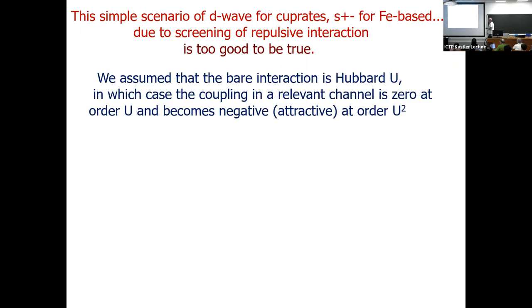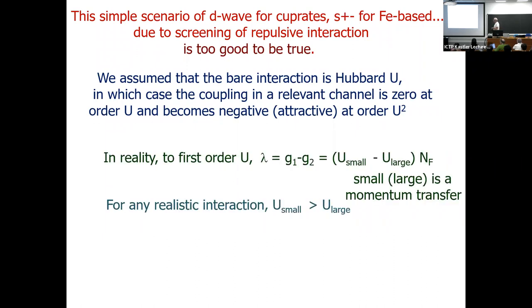Great. But in reality, of course, we never deal with Hubbard interaction. We always deal with screened Coulomb interaction. So it's completely natural to expect that your starting point has this interaction with small momentum transfer and this interaction with large momentum transfer. And it's not rocket science to say that this guy should be larger. You always get a larger initial interaction at small momentum transfer. Which means that you start with repulsion.